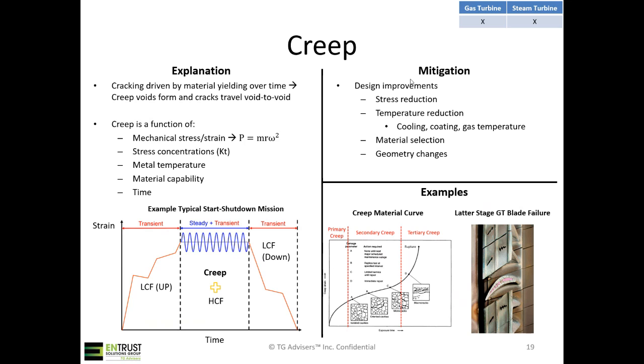Ways to mitigate creep are through stress reduction and temperature reduction. Temperature reduction is a big one. Temperature has a large effect on creep, and you can do that through cooling, the addition of protective coatings or thermal barrier coatings, as well as dropping your gas temperature. The other thing is material selection and geometry changes.